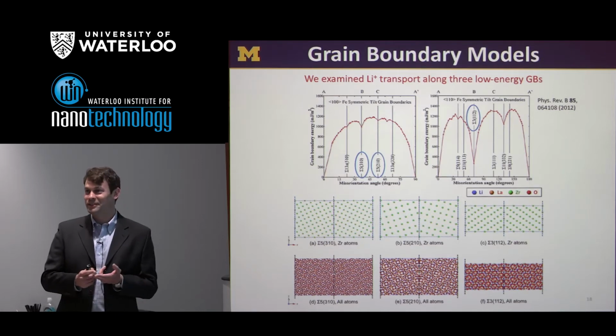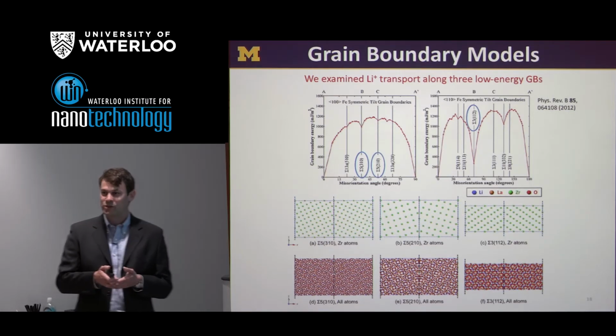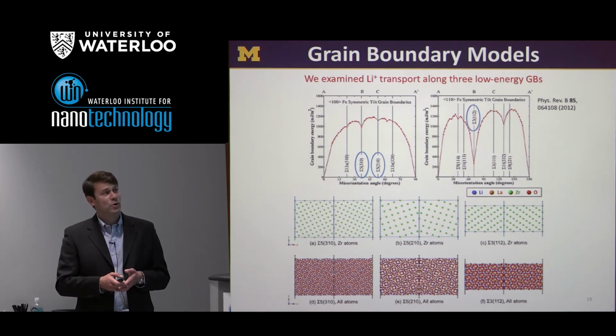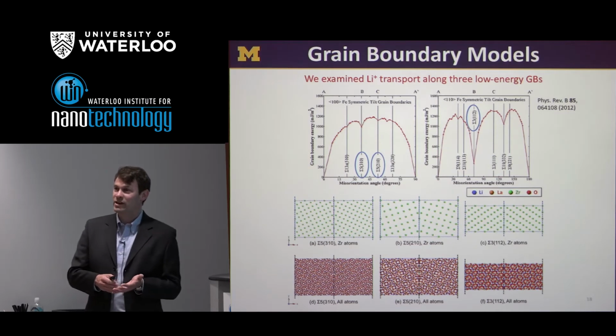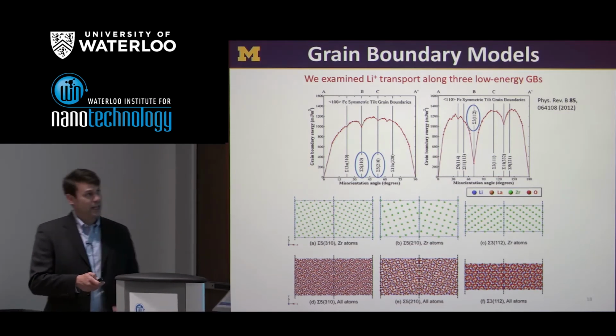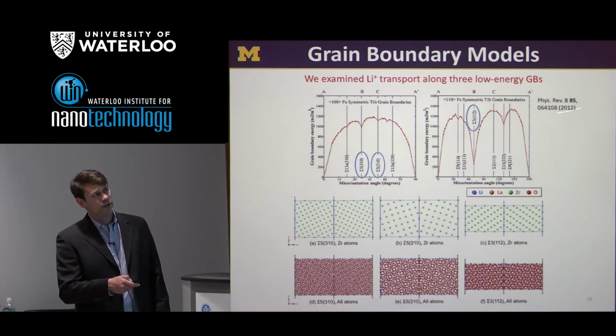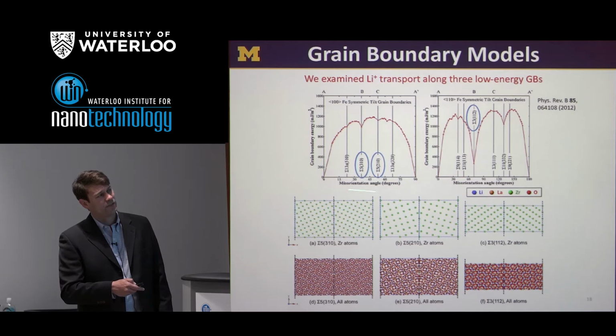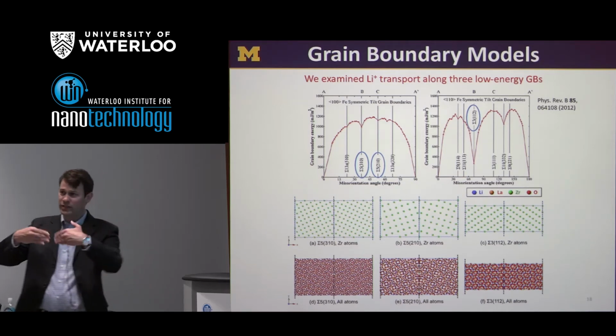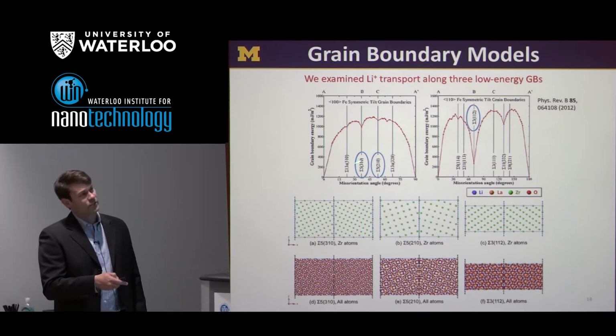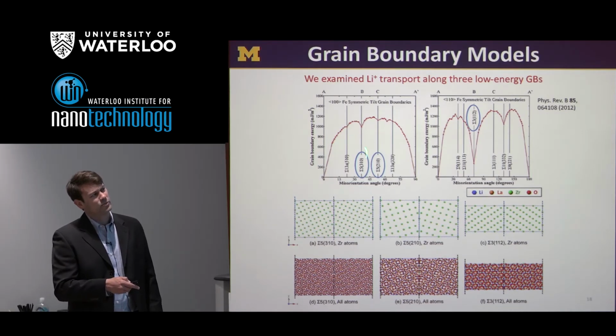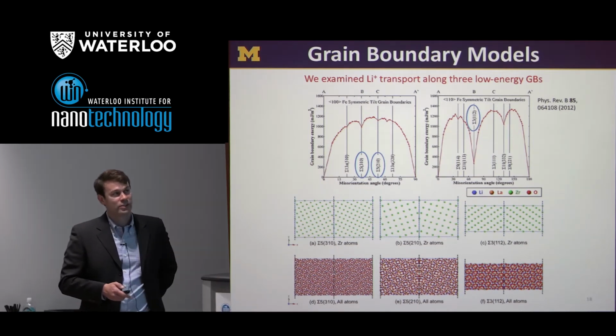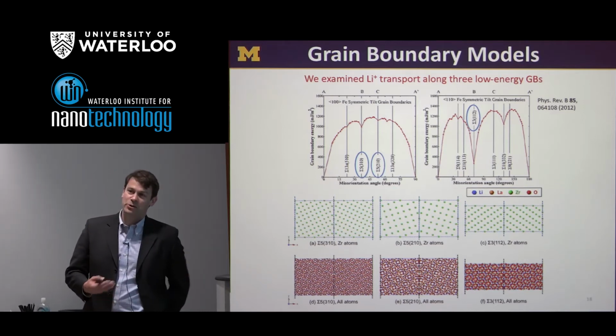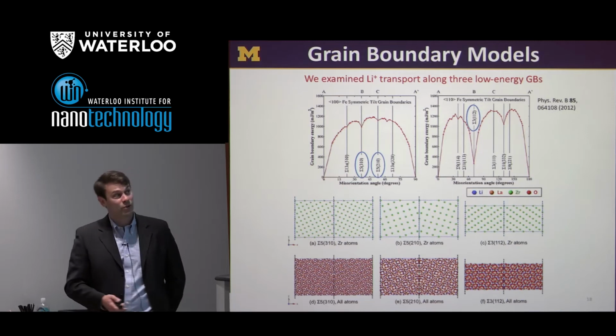A complication, or maybe a reason that few studies exist, is that we don't really know much about the structure of grain boundaries at this point from experiments. So what we have done is use some model systems based on grain boundaries which are known to have very low energies. Here I'm referring to some work based on BCC iron. What's plotted here is the grain boundary energy as a function of misorientation angle between two crystallites that are brought together to form a grain boundary. This is some work from Mark Horstmeyer's group. What you'll notice is that by changing this misorientation angle, there are certain misorientations where we have these notches in the boundary energy. These are special boundaries that have very low energy, and in thermodynamic equilibrium, we would expect them to have some population of the grain boundary network.